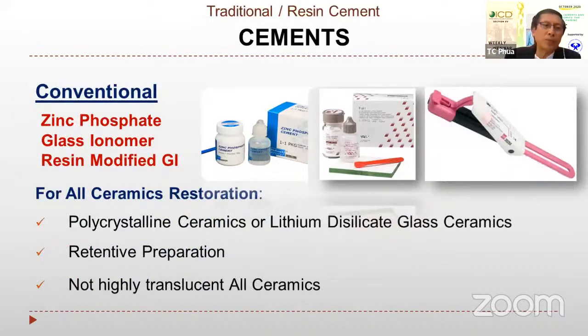And conventional cement, be it zinc phosphate, glass ionomer, or the later resin modified glass ionomer, as represented by some of these representative brands here: we have some Shofu zinc phosphate, there's Fuji 1 from GC, this is RelyX Luting 2, which is actually a resin modified glass ionomer formulation. For all ceramic restoration, we will need it for polycrystalline ceramics, essentially zirconia, or the stronger lithium disilicate glass ceramics that can take this kind of cementation as long as the color doesn't impact it. We need this restoration to have retentive preparation as well. And of course, because of the color of these cements, they are not suitable for highly translucent all ceramics. If you have, say, a very translucent E.max crown, for example, that's not the appropriate material to use.